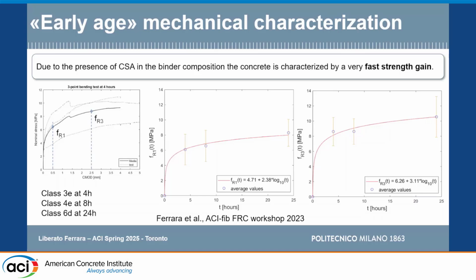It's a notched beam, and you test in three-point bending, and you plot the results in terms of nominal flexural strength versus crack mouth opening displacement. The characteristic value of this first strength, the first one at 0.5 millimeter, gives you this number that you can see here, class 3, class 4, class 6. That means that you have a characteristic value of that residual strength equal to 3, 4, 6 megapascal.